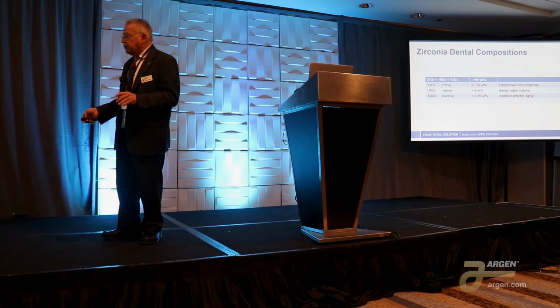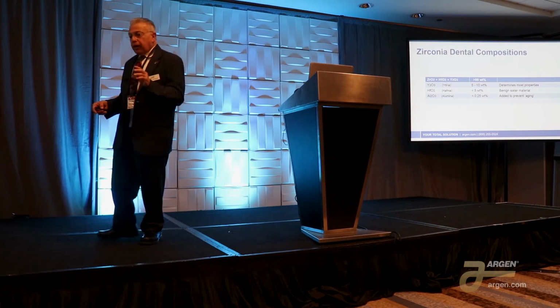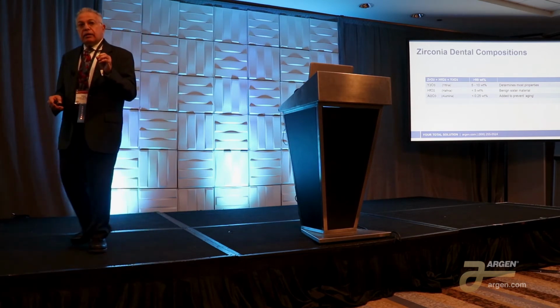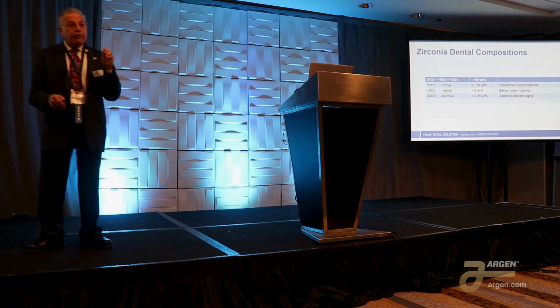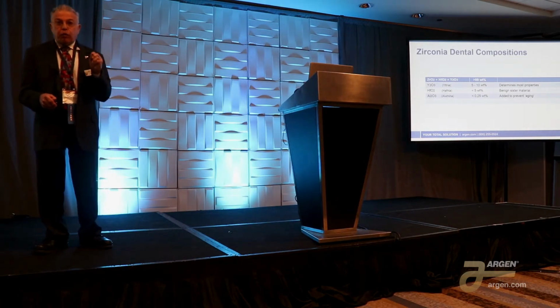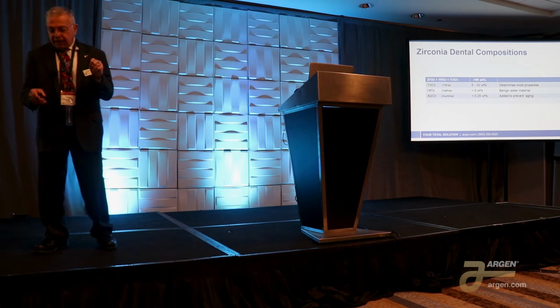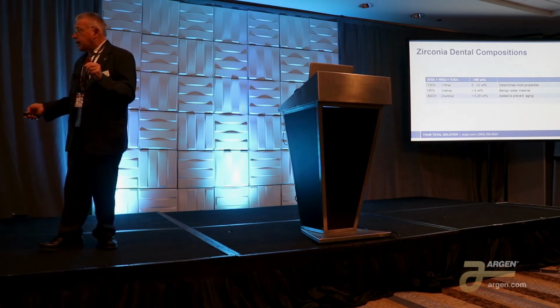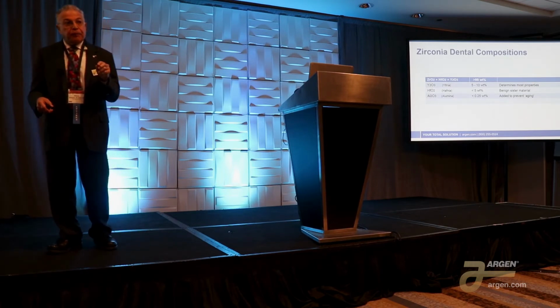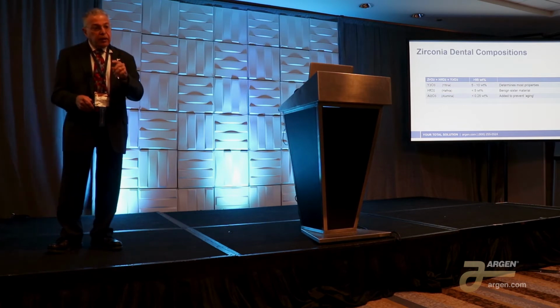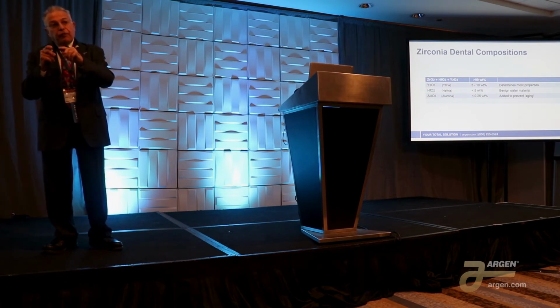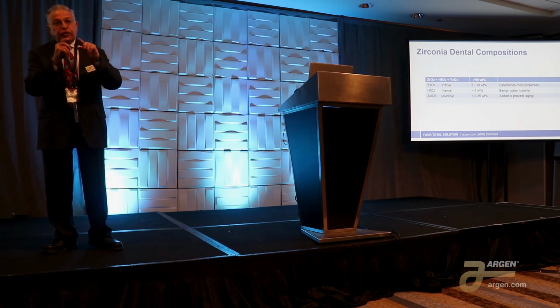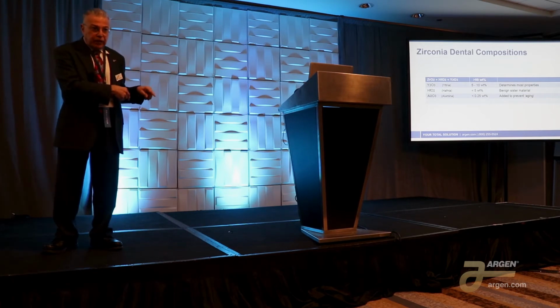Then there's this other element, alumina. One of the reasons why the original zirconia or Lava materials were so chalky white was because they added 0.25% alumina into the composition. That 0.25% alumina was the result of the testing that they did to determine why those hip joints failed.